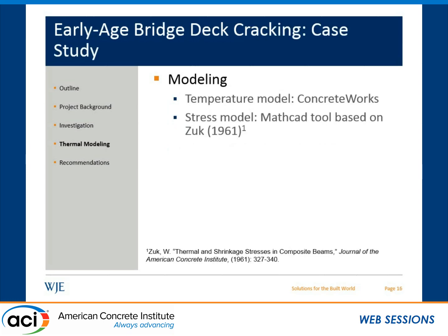So we wanted to determine what's actually causing these early age cracks to develop. We did a number of material tests and examinations, and we determined that one of the most likely causes, or 2 of the most likely causes, are temperature and shrinkage sources. So we did a thermal model. We had a temperature model that we used Concrete Works for. And we also made a very simple stress model. It's more or less hand calculations that we performed in MathCAD based on an analysis from the 1960s by William Zuk.